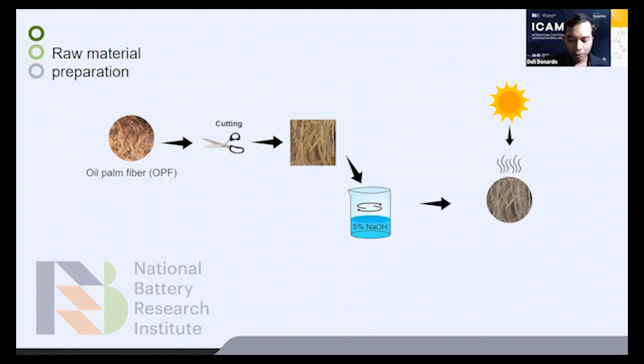First, oil palm fiber was washed thoroughly and cut into small pieces with random orientations along 1 centimeter, then dried in the sun for 1 night. The fibers were then soaked in 5% sodium hydroxide solution in a water bath for 2 hours, and then rinsed in fresh water to neutralize the effect of NaOH and dried at room temperature.